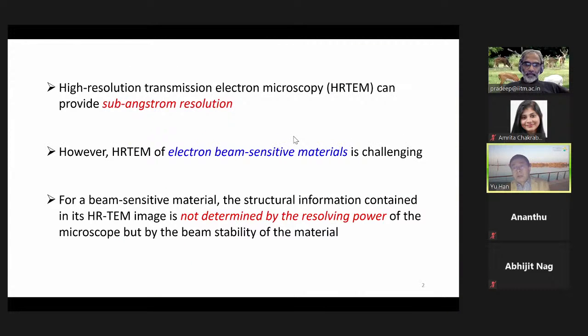So high-resolution transmission electron microscopy, or HRTEM, is one of the most powerful characterization tools extensively used in both materials science and life science. As you may know, a modern TEM microscope can provide sub-angstrom resolution, that is high enough to resolve individual atoms. Unfortunately, however, a large number of materials are conventionally considered unsuitable for TEM characterization. The reason is very simple. They are sensitive to electron beam irradiation. Once exposed to the electron beam, their structure will be immediately damaged, so we don't have a chance to record their intrinsic structures. This is the so-called beam damage effect, or beam damage problem.